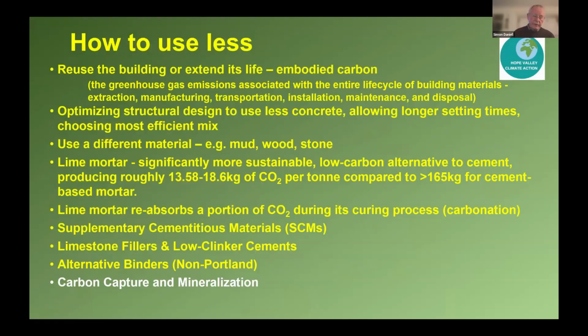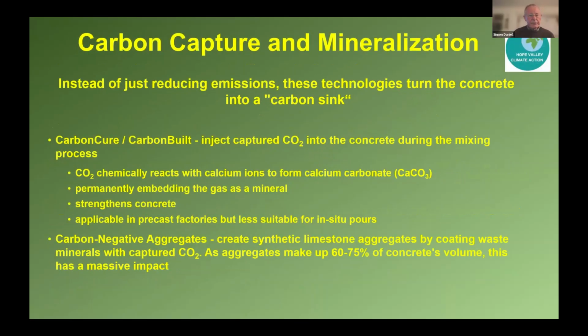cement supply chain. Now, carbon capture and mineralization. This is an interesting one. This is where you actually inject CO2 into concrete while you're making it. The CO2 reacts with the concrete and forms calcium carbonate. So the gas is being embedded in the concrete as a mineral. The advantage is it strengthens the concrete, but you can't really do it on site. But you can do it when you're making precast concrete products. And there's quite a lot of those made.